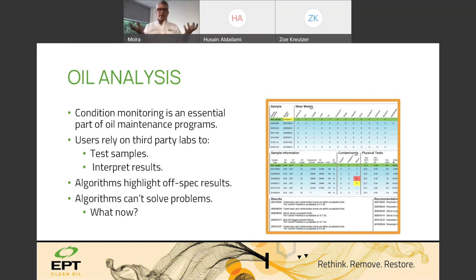I guess my starting point is always to look at viscosity. Viscosity is the number one cause of failure, and you can't fix viscosity. So if your viscosity is wrong, you need to take corrective actions immediately. I would retest that, plus or minus 5% is what I'm looking for. In some cases, you can go up to 10% because there is some variability in the test. But low viscosity is typically suggesting insufficient lubrication film, and the lubricant can't do its job. So that would be more of a concern than, say, 5% too high of a viscosity.